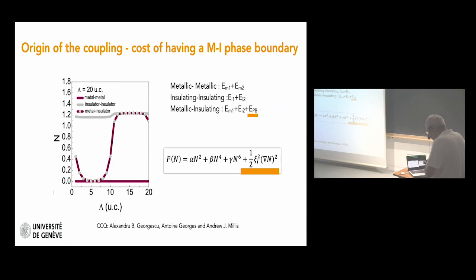We believe that the reason is the cost of having a metal-insulator phase boundary. And this is linked now to the behavior of the order parameter. So this is our n order parameter that I introduced before. And you realize immediately that if both layers are metallic, n is 0 everywhere. If both layers are insulating, n might be slightly different, but it's more or less constant. But now if you have a metallic and insulating interface, your order parameter has to go from 0 in the metallic state to a finite value in the insulating state.